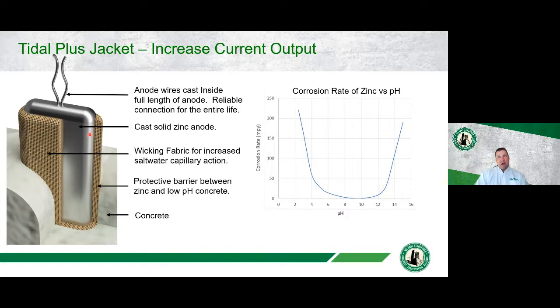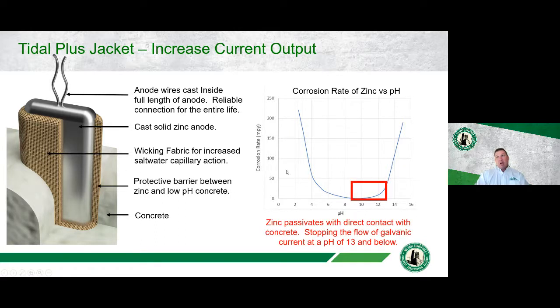And then the other thing that I mentioned previously was that concrete will passivate zinc because of the pH. You know, when concrete is down here at a pH of 10, 11, 12, when zinc is in contact with concrete that is in this zone, zinc will start to passivate. So not only does this wicking fabric help saturate the entire zinc anode, but it also acts as a protective barrier between the zinc and the concrete, so we don't actually have any passivation of the anode due to contact with the concrete.